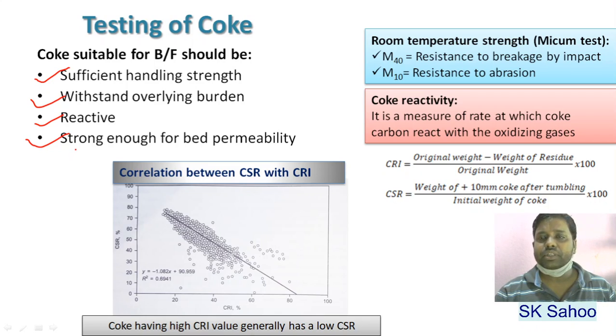So for room temperature strength, we generally go for the Micum index test. In this test, about 50 kg coke sample of 50 to 60 mm size is taken in a mild steel drum, which is rotated for 4 minutes at 25 RPM. Then it is screened with 60, 40, 20 and also 10 mm screens. The percentage mass of coke retained on the 40 screen is called M40, and that passing through the 10 screen is called M10. M40 indicates the resistance of the coke to breakage by impact, and M10 shows the resistance of the coke to abrasion inside a blast furnace.